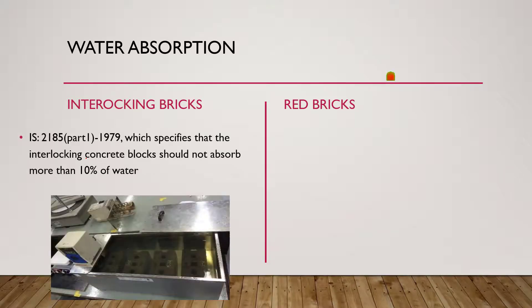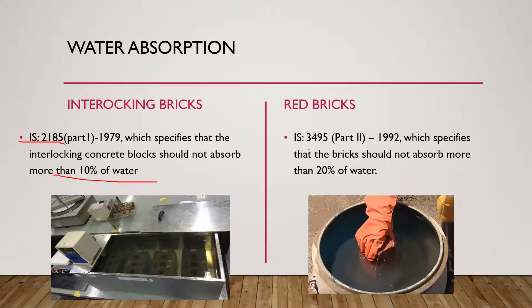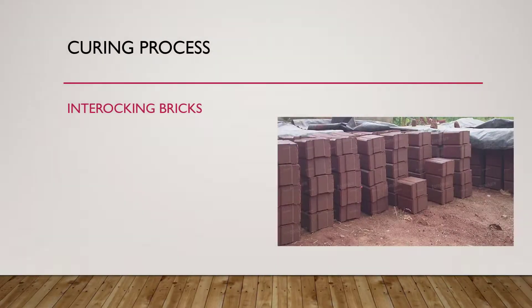Regarding water absorption: as per IS 2185 Part 1 (1979), interlocking concrete blocks should not absorb more than 10% of water. For red bricks, as per IS 3495 Part 2 (1992), bricks should not absorb more than 20% of water.